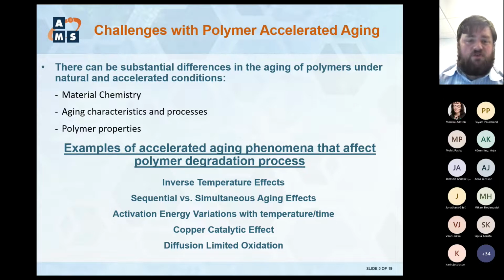So we have to look at those variations, especially when you're looking at accelerated aging versus in-plant, natural aging conditions. Copper catalytic effects, which is something that we've had to deal with, and I'll talk about that in a little bit, but basically at elevated temperatures, we see interactions between the conductor and the insulation polymer, which has implications on our electrical data, and then things like inhomogeneous aging effects like diffusion limited oxidation. And this is just a few examples of the types of things that could happen, but it's really just trying to summarize the different types of aging processes. The simplistic idea of accelerated aging, okay, we have a simple aging process, becomes much more complex and complicated, and you have to actually go in and try to figure out what's actually happening to the materials.